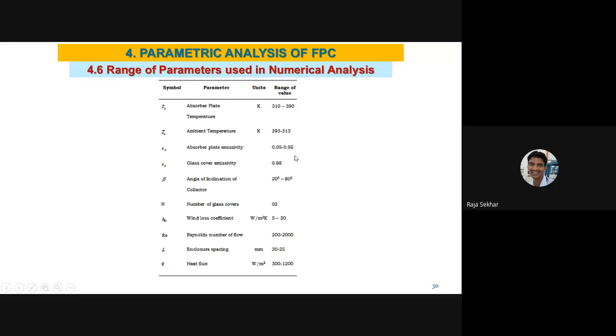And for the absorber plate emissivity, we have changed it from 0.05 to 0.95. Why this change? 0.05 means we have proper selective coatings where the emissivity of the absorber plate is reduced. And 0.95 is the emissivity of an absorber plate coated with normal black paint. Whatever commercial paints you get, if you paint it, the emissivity will be 0.95.